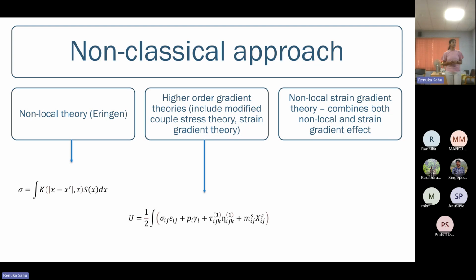Then we have higher order gradient theories, which include modified couple stress theory or strain gradient theory. Here they include the gradients of the strain also in the strain energy definition. The classical strain energy definition is just up to the first term, but these higher order strain gradient theories consider the gradients of the strain as well when defining the strain energy functional. And then we have a combination of the two, which is the non-local strain gradient theory, wherein the stress is taken from the non-local theory, and the strains and the higher gradients of the strains are also taken. So these are the commonly used theories in literature, which comprise the non-classical approach.